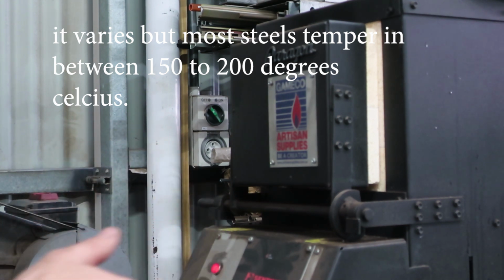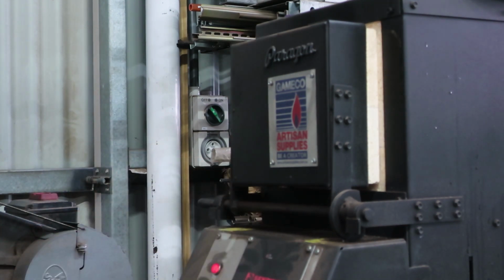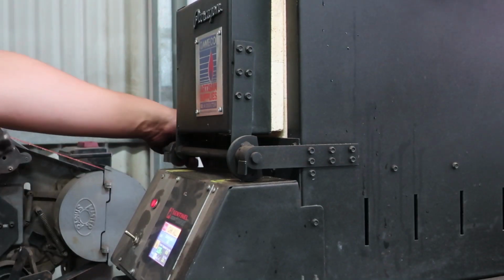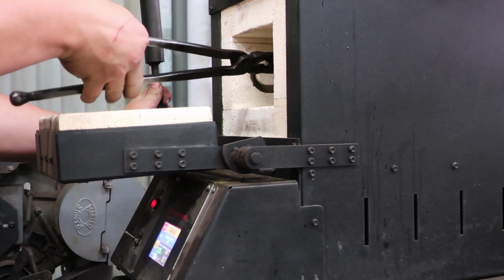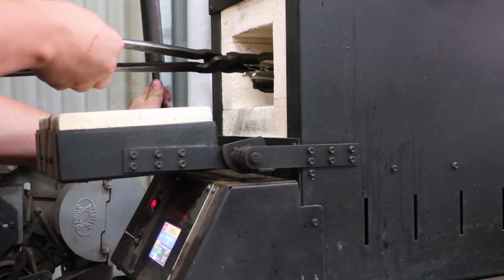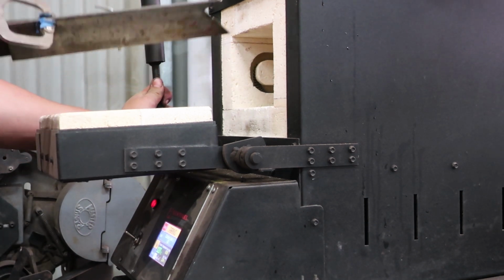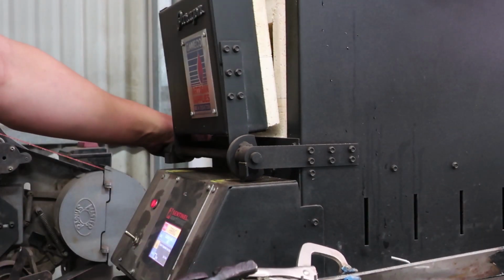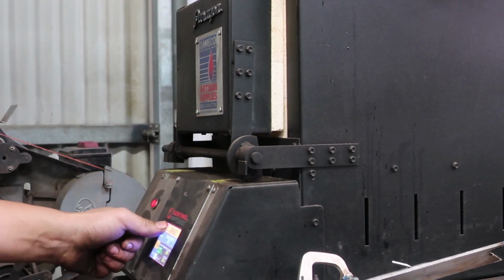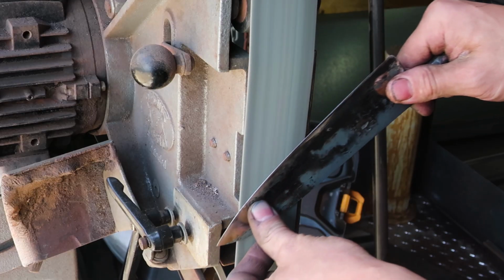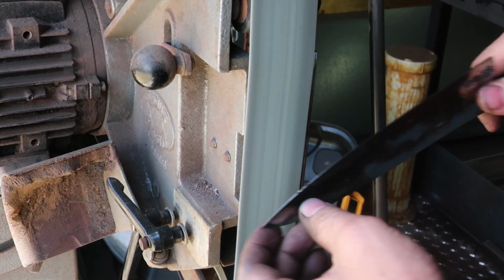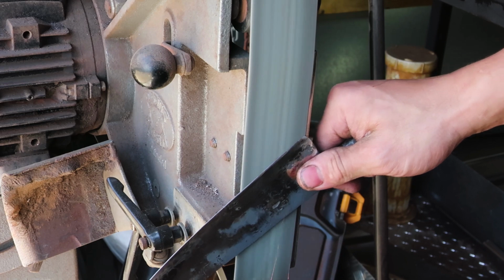Now, I actually had a pretty bad banana edge on the knife, which is not good. I had to forge it flat and normalise and repeat it till it eventually stayed straight, but in the end I got it pretty good. With that being said, I do have a warp in the blade which I can get out with a shin temper. But make sure the knife is completely cool when you take the clamps off when you do a shin temper. So I do have 2 inclusions in the spine which are stress risers and could snap the blade, but at this point I'm just gambling that it'll be alright.